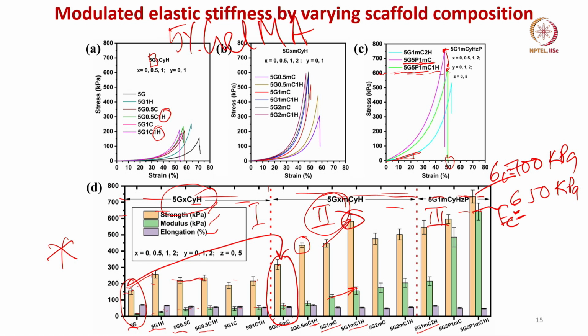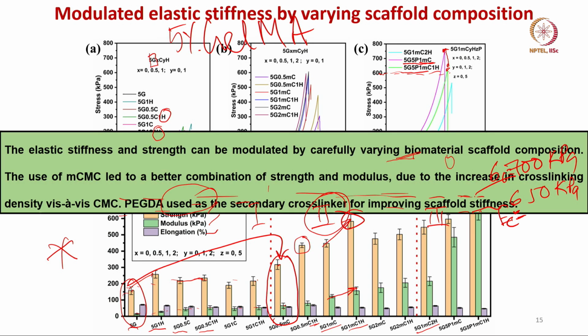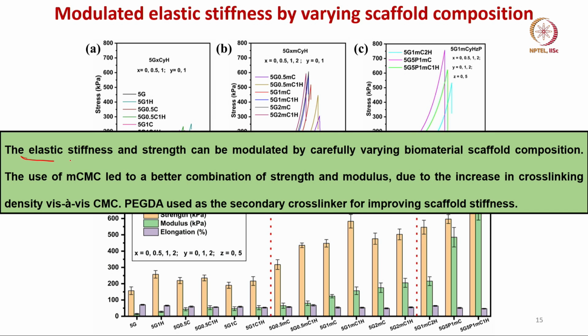Now, what I am trying to address here is that by changing the hydrogel scaffold composition, by carefully adding inorganic fillers like hydroxyapatite, both the elastic stiffness and strength can be modulated, right. The use of modified carboxymethyl cellulose led to a better combination of strength and modulus due to the increase in cross linking density vis-a-vis plain CMC, and PEGDA is used as the secondary cross linker here for improving the scaffold stiffness. So, this was the design of the hydrogel composition that was pursued, and it has a very positive impact as far as the uniaxial compression properties are concerned.